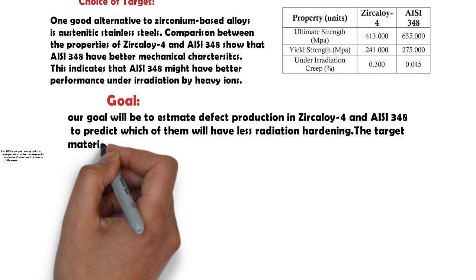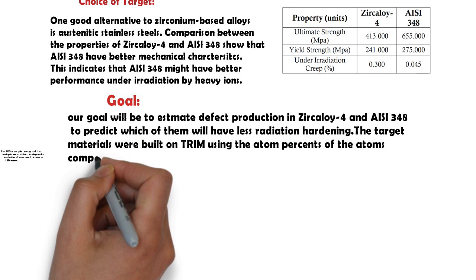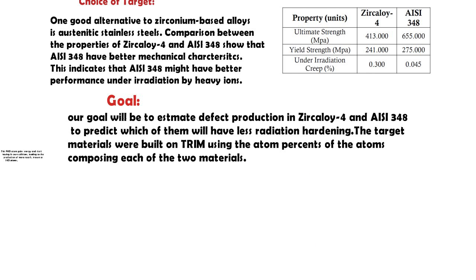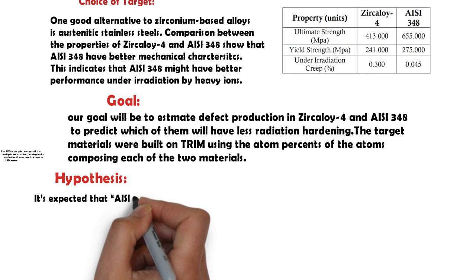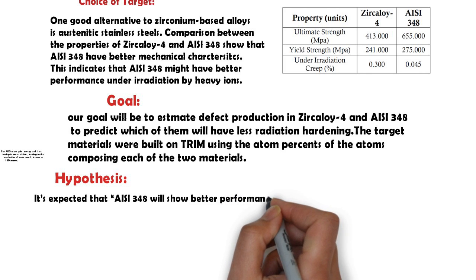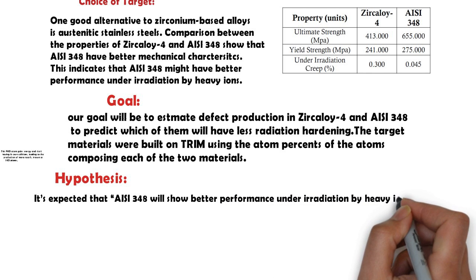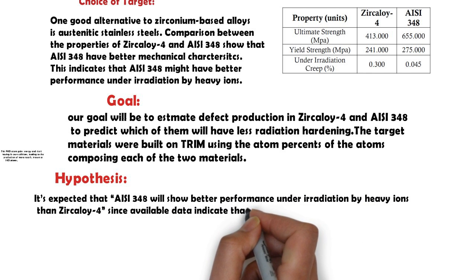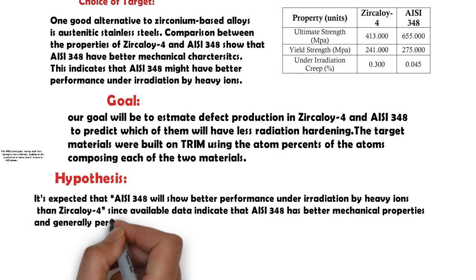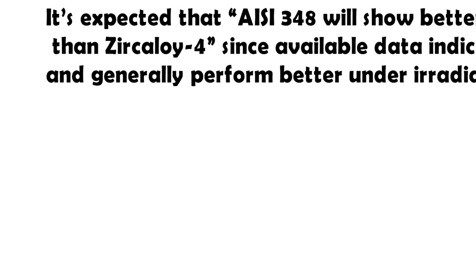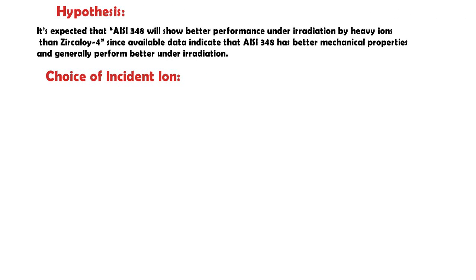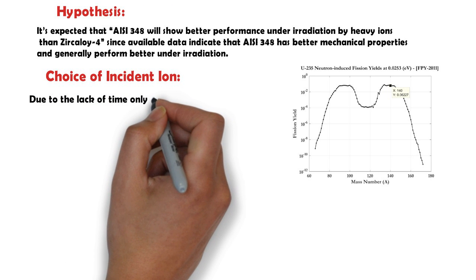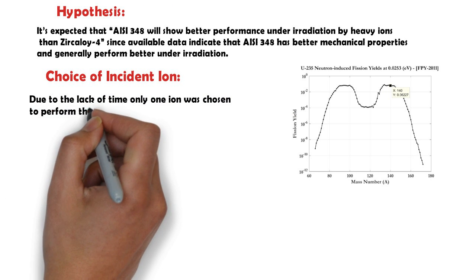The target materials were built on TRIM using the atomic percents of atoms composing each of the two materials. It is expected that austenitic steels will show better performance under irradiation by heavy ions than zircaloy 4, since available data indicate that stainless steel has better mechanical properties and generally performs better under irradiation. Due to the lack of time, only one ion was chosen to perform this experiment, xenon 140.